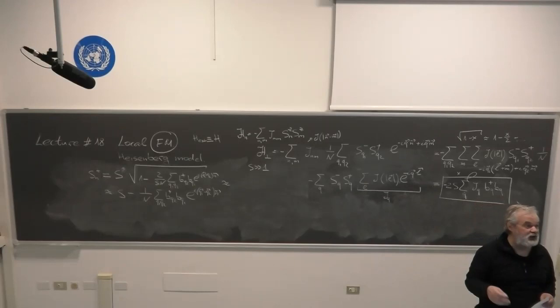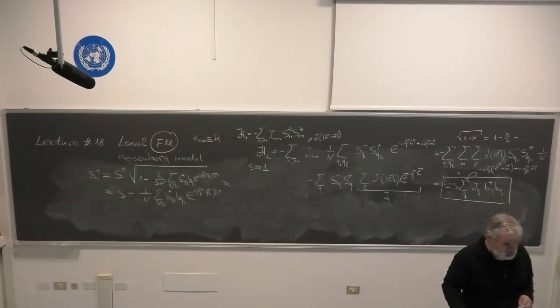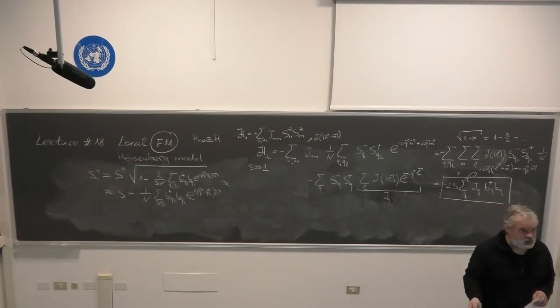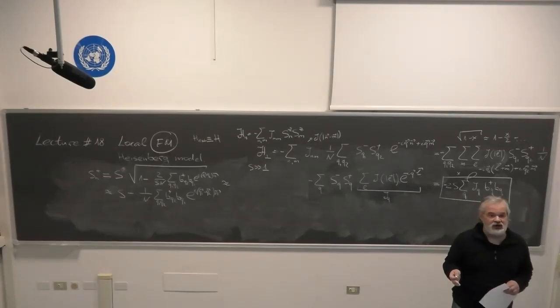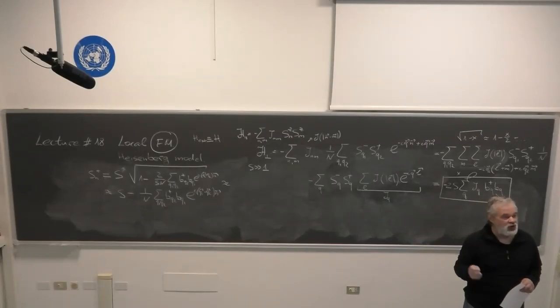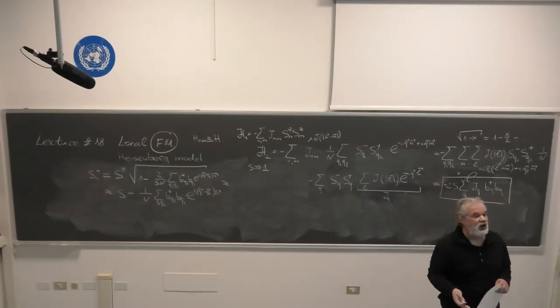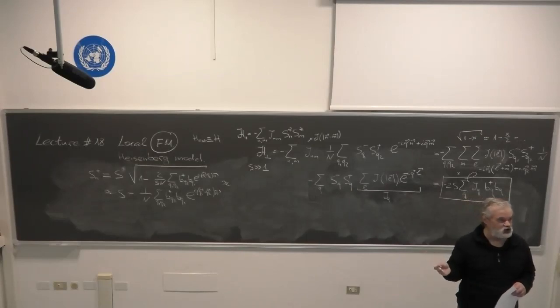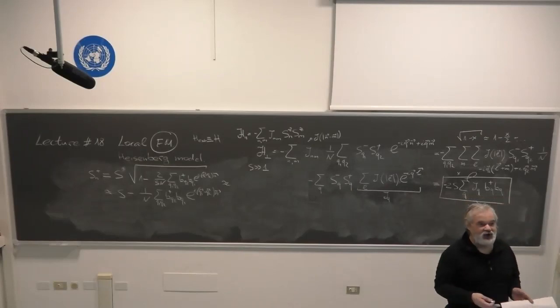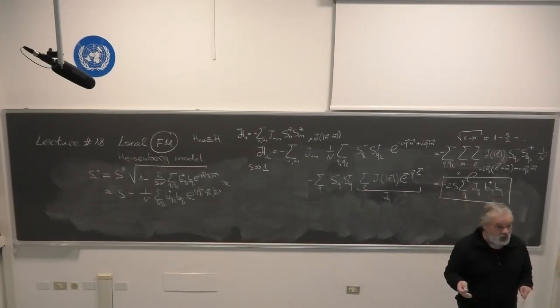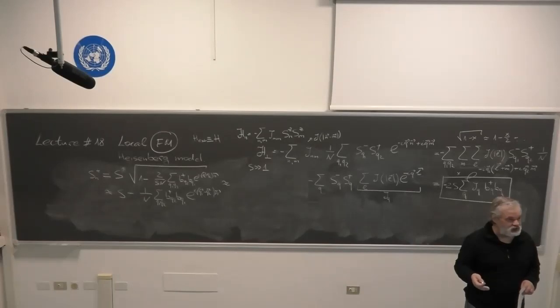But if you do it and you compare the results of the magnon spectrum, which I'm going to derive, with experimental measurement, you still have good quantitative agreement. However, as I said, to be on the rigorous side, the legitimate way to do it is either for large spin or large coordination number. For the simple cubic lattice, the coordination number is 6, so 1 over 6 is a good small parameter. The real expansion is in terms of 1 over 2S. If spin is equal to 1/2, 1 over 2 times 1/2 is 1, and 1 is not a small parameter. However, as I said, it works fine also for spin 1/2.